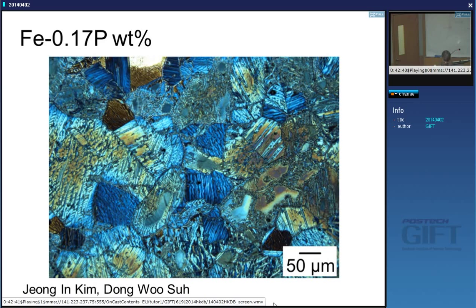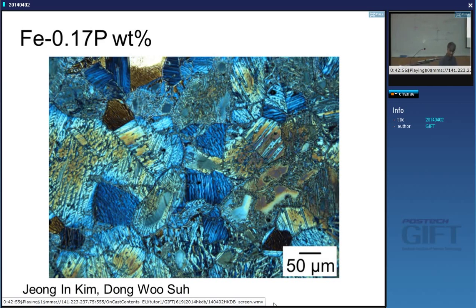You develop this thermal groove, which you can see very clearly when you cool the specimen down. So from this you get a very good measurement of the austenite grain size, because these grooves are very clear in the optical microscope. Of course, you might also get some oxidation which will color the surface. This is shown in an iron-phosphorus alloy where there is some oxidation of the grains, which helps etch the austenite grains at high temperature, and there are thermal grooves visible. This is an iron-phosphorus alloy, so you get massive transformation — you nucleate ferrite grains that simply grow across many austenite grains.